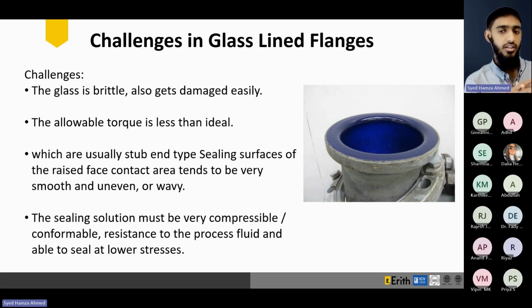It creates a raised face contact area that tends to be very smooth, and in some cases even uneven, or wavy, because of the glass lining. Due to the process involved in glass lining, this is mostly the case where these edges are not entirely even, and this creates another hurdle and another challenge. Therefore, the sealing solution for this type of flange has to be very compressible as well as conformable, while being resistant to the process fluid and able to seal at lower stresses. So there's a huge challenge in a flange that is lined with glass.